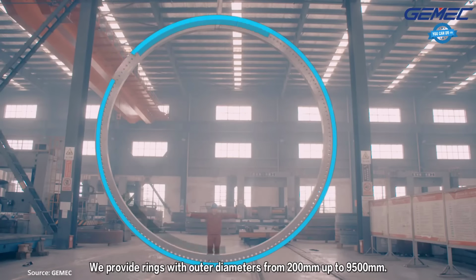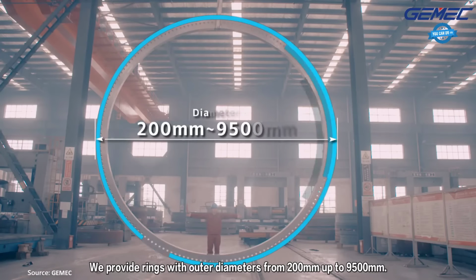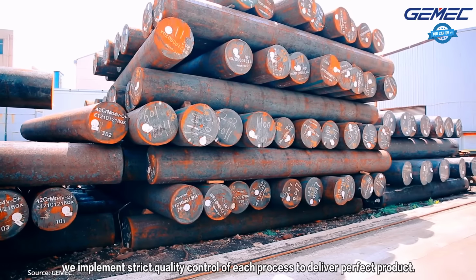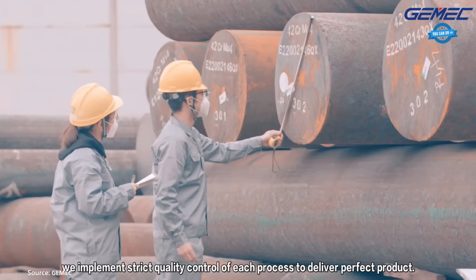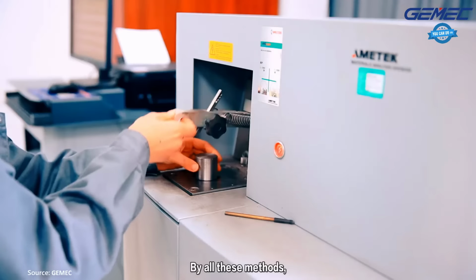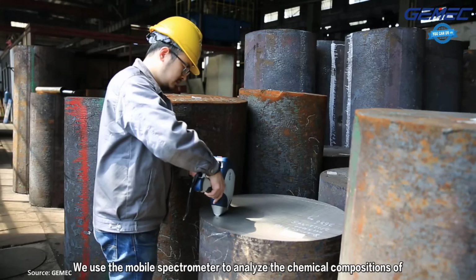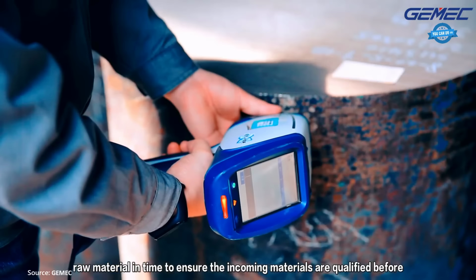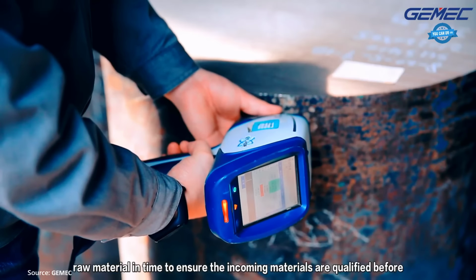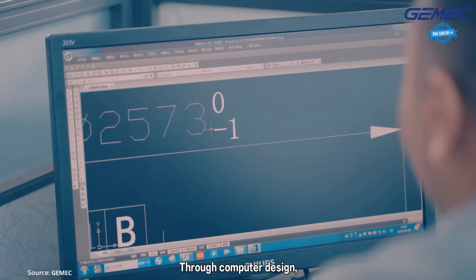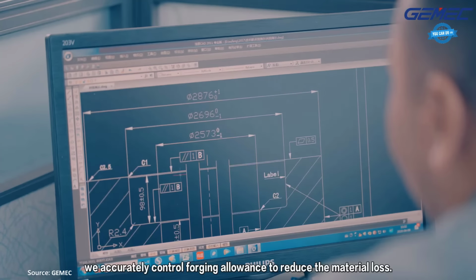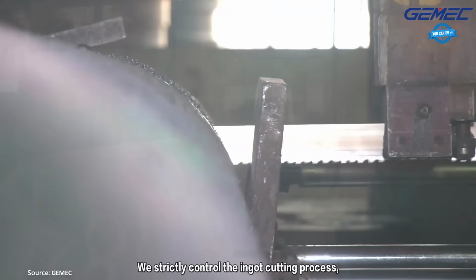From a raw steel ingot to a high-performance rolled ring. At GEMEC, production begins with carefully selected steel grades. Mobile spectrometers check raw material compositions on arrival, screening for unwanted elements like sulfur, hydrogen, and oxygen. Ingot cutting is tightly controlled via CAD models to avoid contamination from risers or gates.